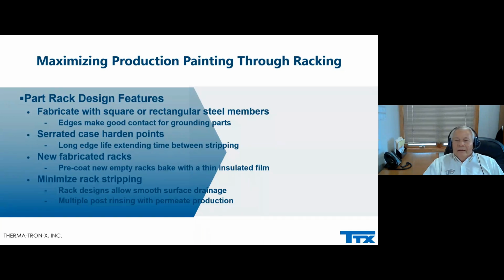If you're using conventional spray guns, it's no problem because conventional doesn't have electrostatic attraction. But if you're using electrostatic powder or electrostatic liquid or even e-coat, you really need to make that surface break every time you put a part on it. So what we're looking at here is fabricate the racks with square and rectangular steel members. The edges make good contact for grounds. Serrated case hardened points are very good for maintaining ground. Even if you have up to half a mil, those serrated edges will break it. It will break that surface, and by having them hardened, they're not going to be wearing so much.